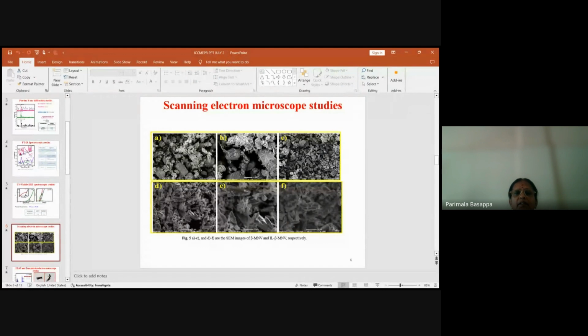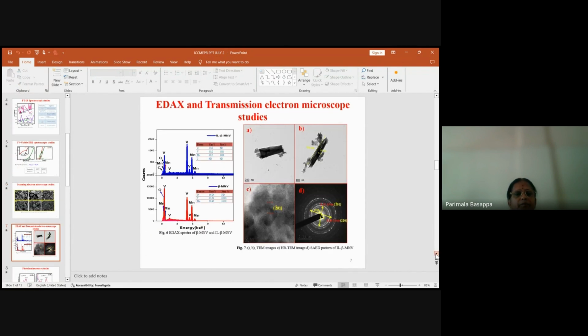So the SEM study shows this is the A, B, C images of beta MNV, and these are the images of ionic liquid beta MNV. You can see the difference here. You have almost agglomeration-like products, but when treated with ionic liquid, rod-like structures were observed, which shows that the ionic liquid acts as a surfactant to improve the shape of the compound we have synthesized. TEM studies we have also carried out, and they correlate with the SEM studies. The EDAX study shows that it mainly contains oxygen, vanadium, and manganese.